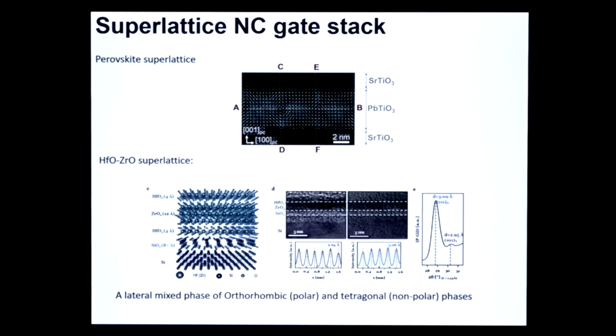And so we came back to what our learning was in the perovskite-based systems. In the perovskite-based systems, what we learned is that this superlattice, remember, allows the ferroelectric to break into domains. And in the suppressed polarization regions, we see very large negative capacitance. So what we started doing is we started making superlattice-like structures with hafnium zirconium. The particular superlattice I'm showing here is a 4 angstrom hafnium dioxide, 12 angstrom zirconium oxide, and 4 angstrom hafnium dioxide. So this is really, in my mind, atomic engineering. You are really going by unit cell here, right?